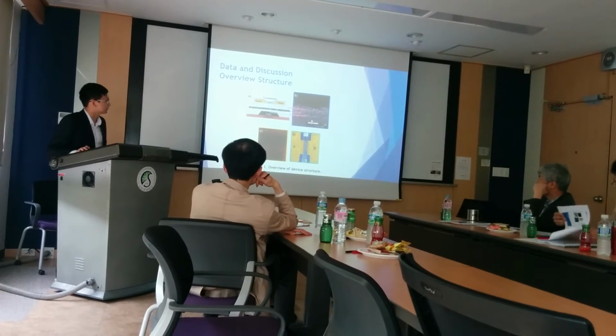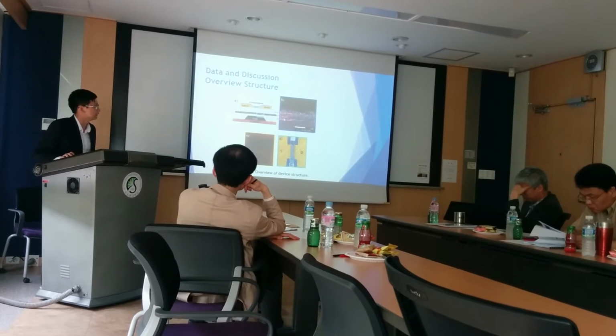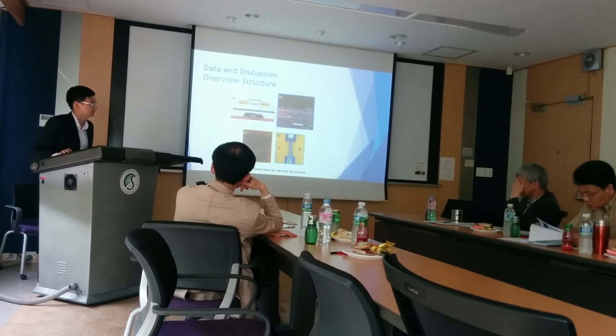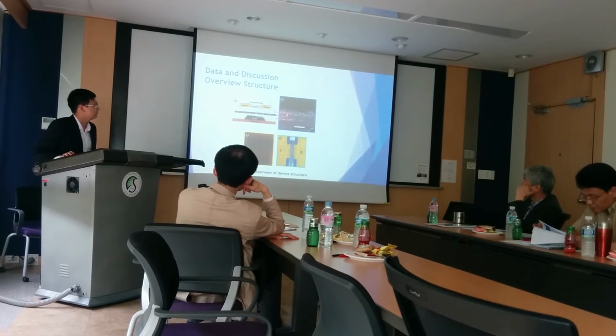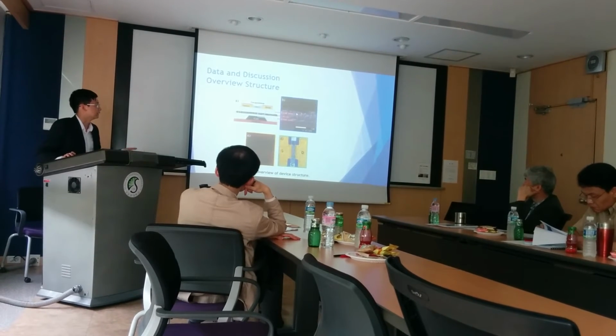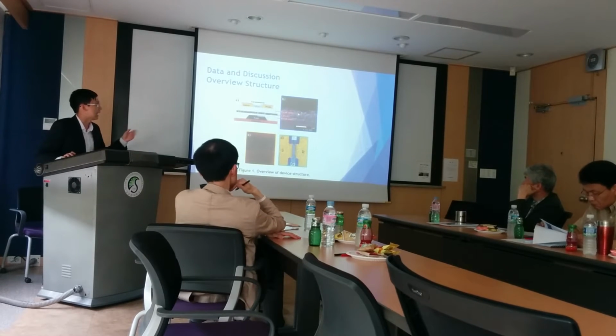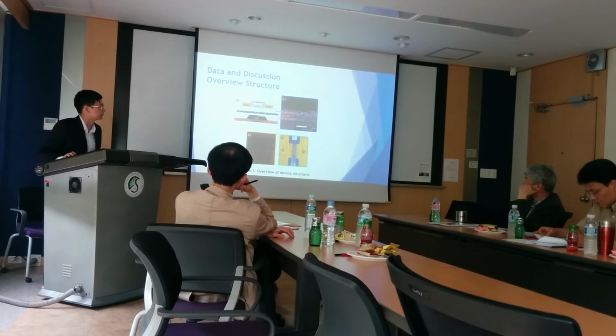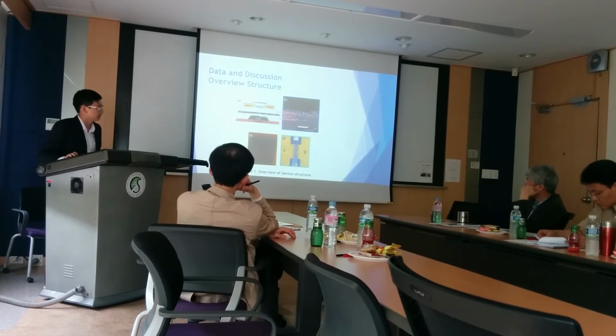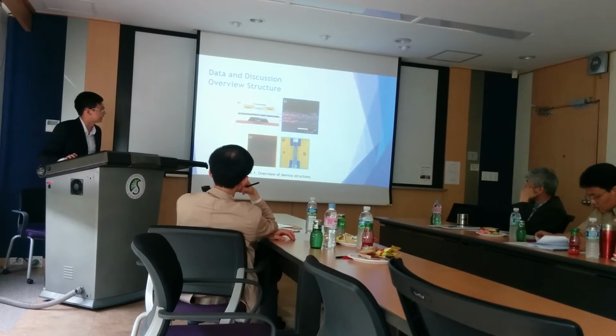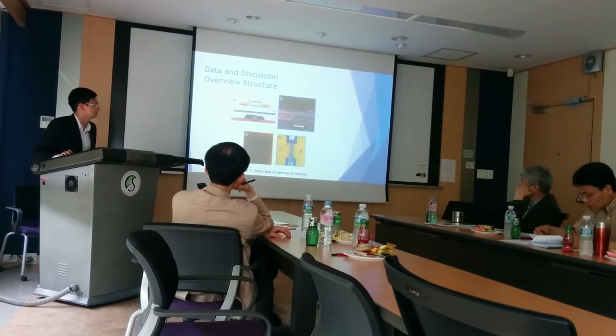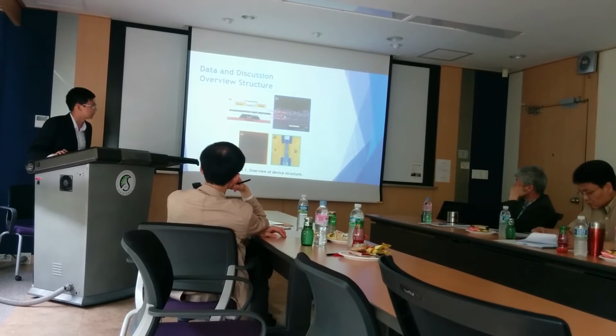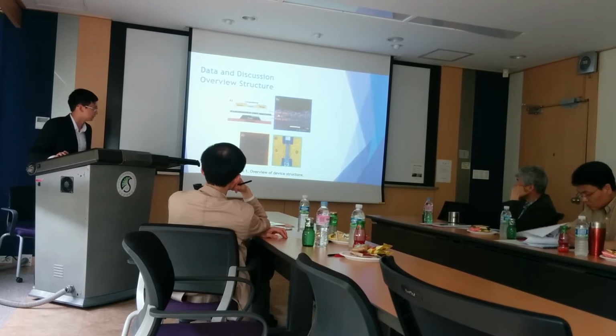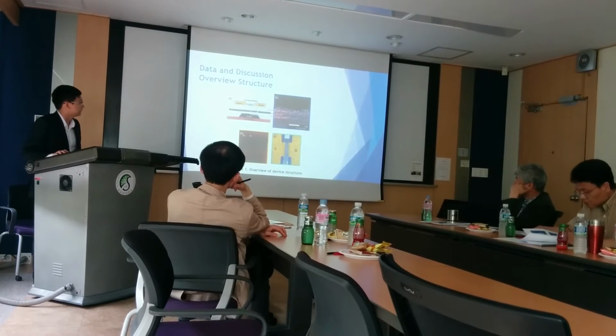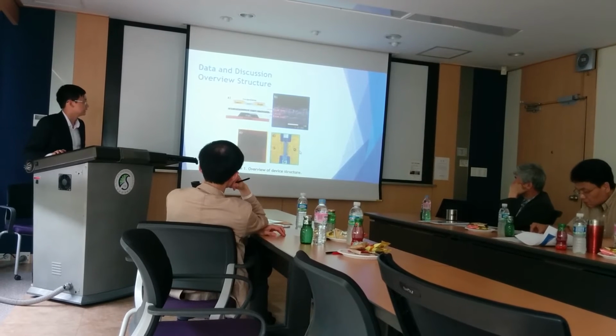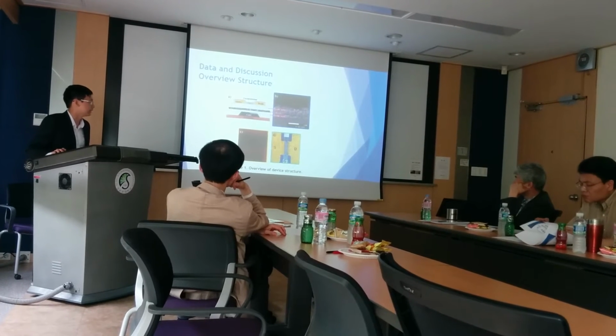As you can see, the cobalt ferrite CFO is sandwiched between two layers of PVDF-TrFE. PVDF-TrFE is developed by crystallization from annealing at 140 degrees for 2 hours and then reducing the temperature to make the crystallization. Cobalt ferrite is deposited by the drop-casting method and the solvent ethanol is evaporated to make a thin layer. And figures 1C and 1D show the top view of our device.